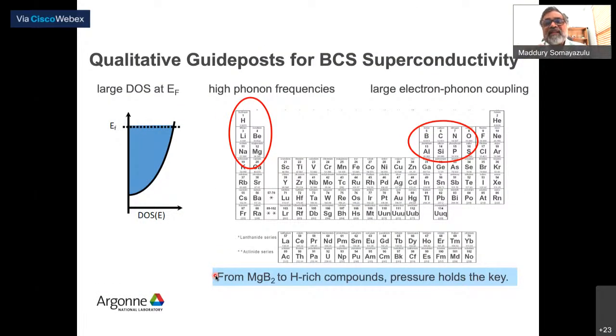But I think it was at that time there was a reassessment of where these molecular hydrides are going. And I'm picking up a slide which was presented by Neil Ashcroft, in fact, in one of our meetings, where he pointed out that, look, what you want is high phonon frequencies, right? From a BCS perspective, I'm assuming all of us are fairly familiar with BCS theory, what you want is high phonon frequencies and large electron-phonon coupling. Quite simply, if we just stare at the periodic table, it means that you want to combine elements here, like hydrogen, lithium, beryllium, sodium, magnesium, with elements on this side of the periodic table, like boron, carbon, nitrogen, oxygen, and so on.